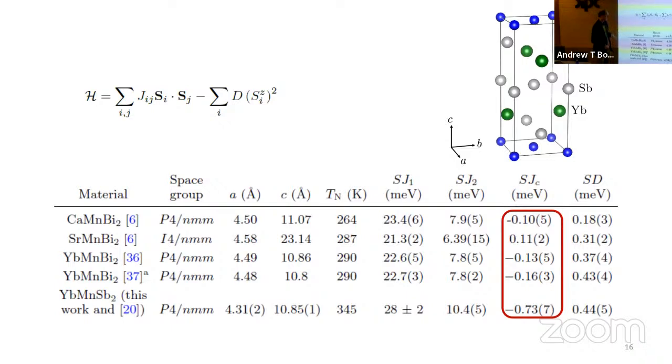And it could be then that because antimony is smaller, the antimony orbitals are more tightly bound to the atoms. So the super exchange part of the exchange is probably suppressed, is probably lower. And the electronic, sort of metallic part of the exchange may be the same strength as in the bismuth compound. But that then, relatively speaking, is the bigger exchange contribution. So we think that in the antimony compound, the effect of the topological electrons in this level here is probably more important than in the bismuth compounds. So it might be a good material for studying experimentally the effects of topology, the coupling between topology and magnetism.